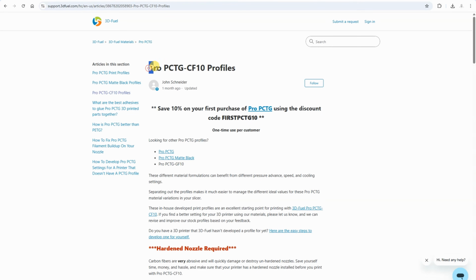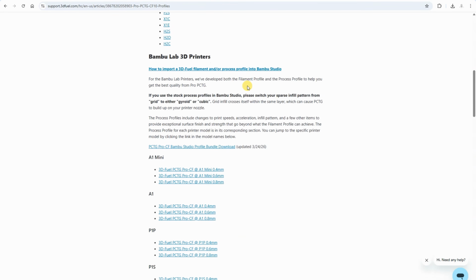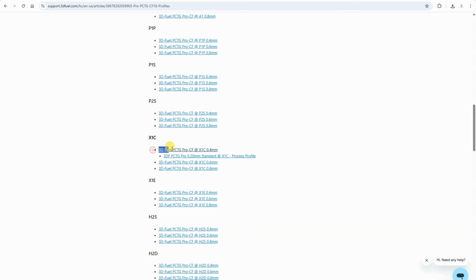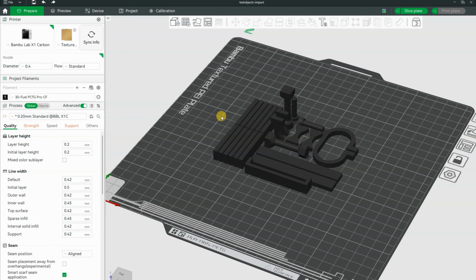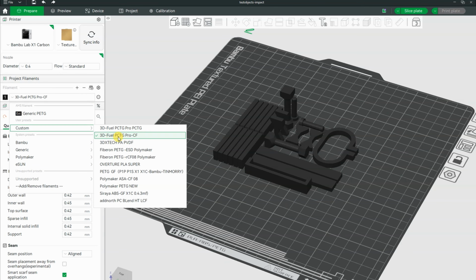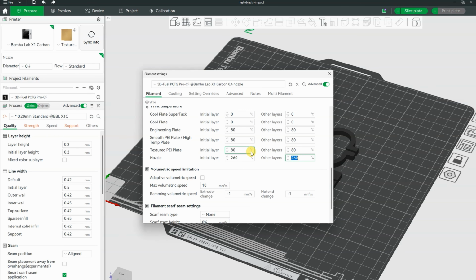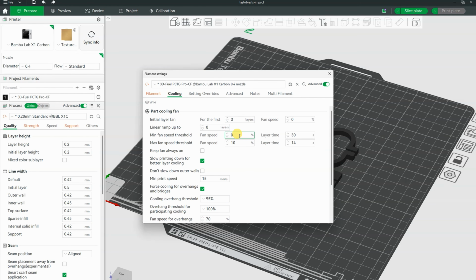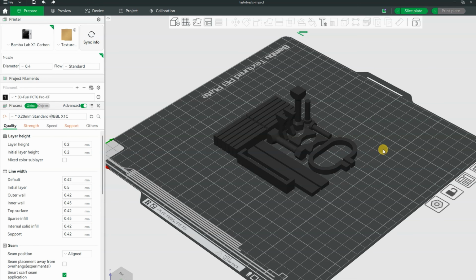3D Fuel offers a profile for their filaments. This is for the carbon fiber version, and the printing will be on the X1 Carbon. These are my regular test objects, and let's set that profile. This is the carbon fiber version. I changed the nozzle temperature to 270 because this is the maximum recommended, 80 on the bed, 10 the maximum flow rate, and part cooling between 0 and 10%.